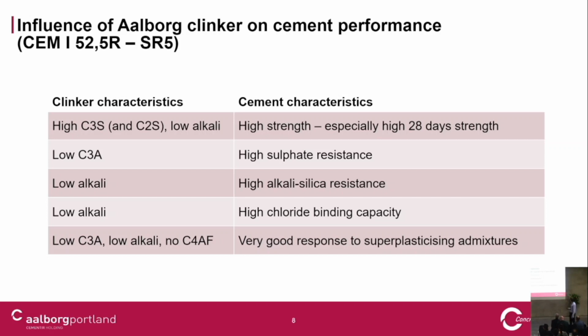The low C3A allows us to have a sulfate-resistant cement. The low alkali content allows us to have a cement that will never have harmful alkali-silica reaction. You will not see it with the white cement.